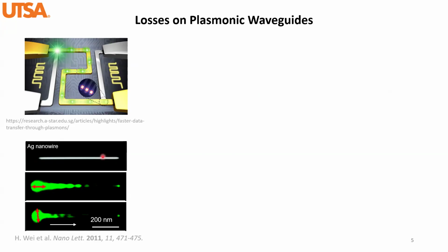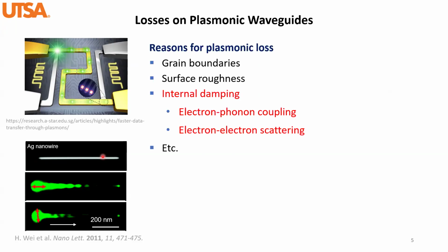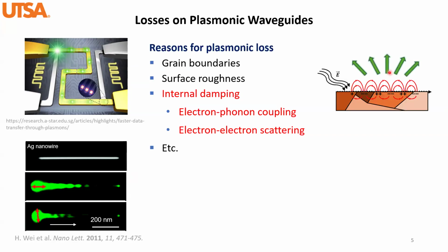So it sounds really promising because you have highly confined light and enhanced optical intensity in the near field. However, it suffers from significant loss that is caused by multiple reasons. One is grain boundaries, and another is surface roughness. And something related to the intrinsic property is the internal damping. So in terms of grain boundaries and surface roughness, if the electron oscillation travels across a grain boundary, or travels at the surface and the metal has a rough surface, it causes some losses.